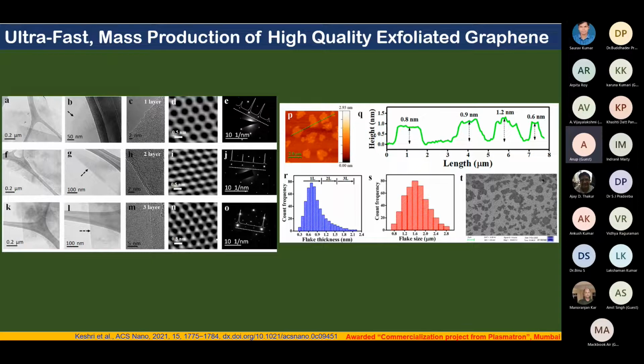Now the left hand side shows a much deeper investigation by HRTEM. In image A, you are seeing the low magnification image, and what we found is a very transparent flake, which you can see over the copper grid. In image B, a slightly higher magnification image, if you follow the arrow mark, it shows some kind of transparent flake. It is not quite visible because we believe it is a single layer.